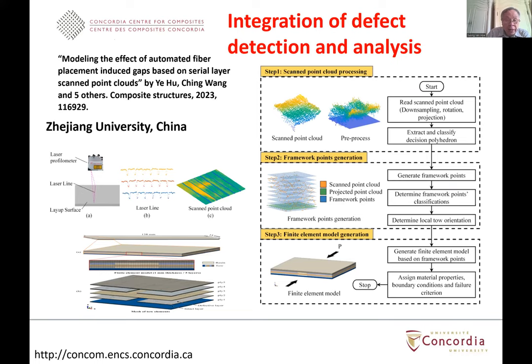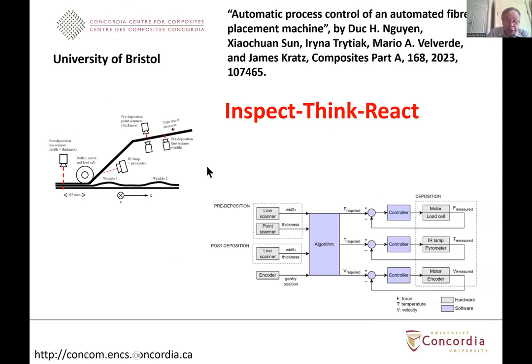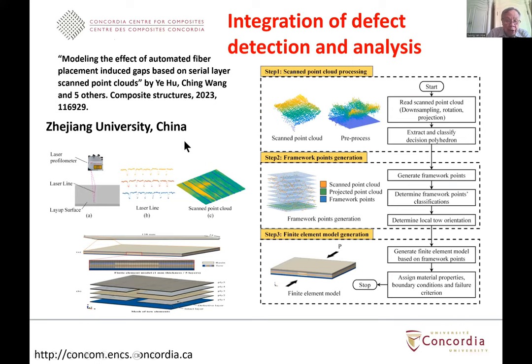In this case, recently there has been some work done in trying to integrate the defect detection and the analysis. There was a publication this year from people at Zhejiang University in China. What they do is they first scan the surface of the structure, then they get many scan points and distribute them into different layers. From these layers, they put them into a finite element model. Each layer may have some kind of defects, and they run analysis subject to some kind of loading to see the performance of the structure. So they want to integrate defect detection and analysis to see the effect of the defects on performance using modeling rather than real experimental data.